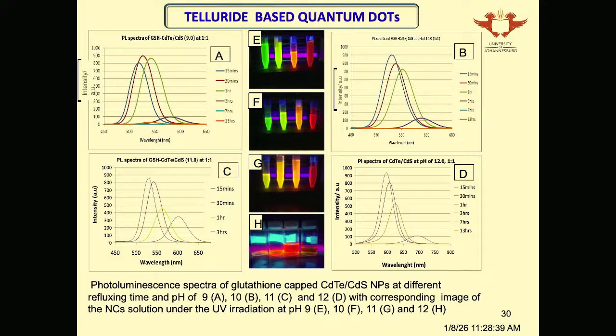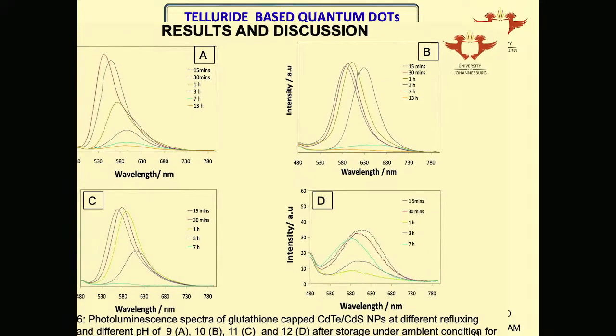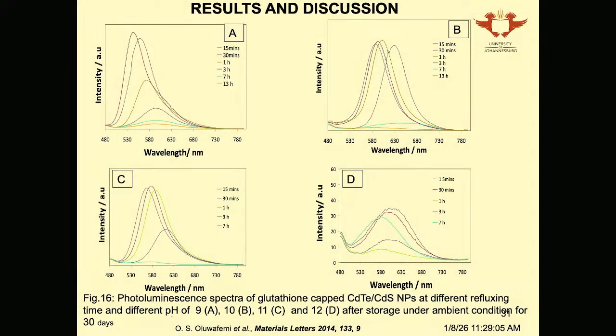We are very excited. And then our application. Then we moved from the excited state back to the ground state. Because by the time we applied this material, it destroys all the cells. Number 2, the material was not stable. And that is what this is all about. You can see this is pH 9, 10, 11, 12, 30 days, the thing quenched.